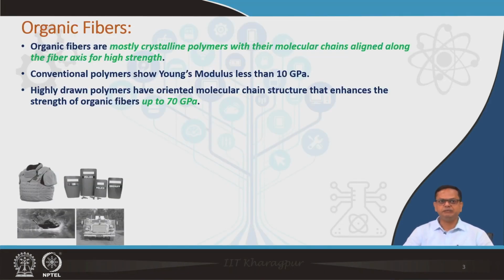Organic fibers are basically polymeric fibers. You have polymer material, and the idea here is to align the long chains in the axial direction and make the fibers like that, so that you achieve fairly high strength and modulus. Obviously, polymer materials do not show very high modulus, in the range of 10 GPa. If you can align the polymeric chains properly, then you can have higher modulus. As you can see here, the data mentioned is around 70 GPa.